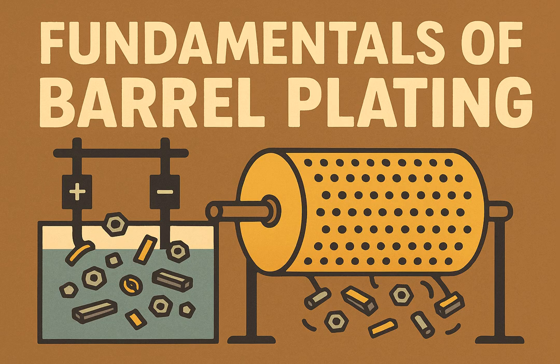Okay. Any other quick examples of problems? The sources mention other issues too, like a low plating deposition rate if the bath pH is too low or current density is insufficient, or issues with the anodes themselves becoming passive and not dissolving properly, starving the bath of metal ions. They also touch on challenges plating on specific alloys like leaded brass, which might require special acid dips before plating, or the impact of plating thickness on dimensions, such as increasing the pitch diameter of threaded parts. It's a complex ecosystem of chemistry, electricity, and mechanics where many things have to go right simultaneously.